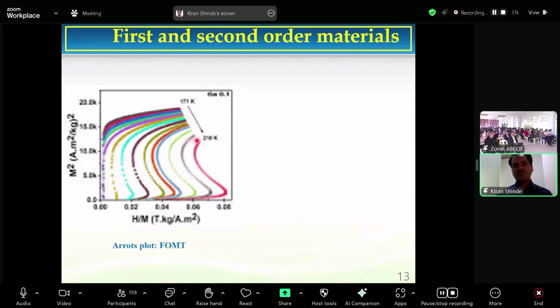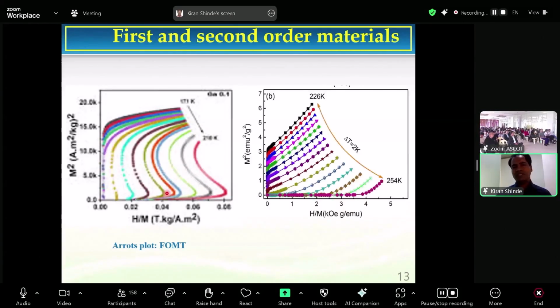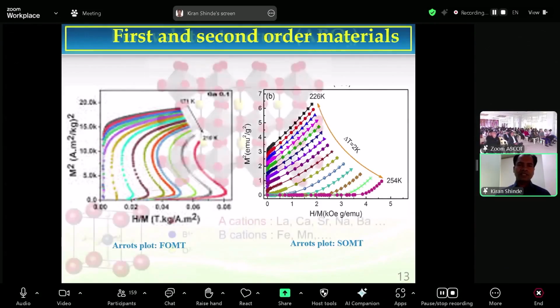When they have negative slopes, we can say they are first order transition material, and when they have positive slopes, they are second order transition material. But in first order, we can see that there is a negative slope, so they are confirmed as having the first order phase transition material. Here we can see that on the right hand side, all the Arrott plots at different temperatures are showing positive slopes. So we confirm that the material is second order phase transition material. So we have to confirm this first before going further for detailed study in this kind of materials.